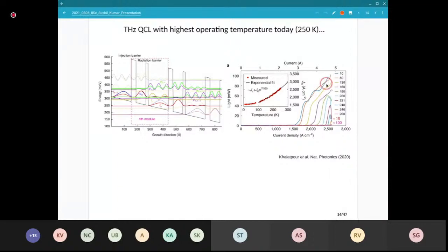But that does not mean that you can just cool them with some cooler and have them working. This kind of figure, I'll show you some more of. This is current and this is light. That's how a laser is typically characterized. These are called LI curves, light versus current. When you keep increasing the current through this device, it starts to lase and emit light. This is laser light, and the power keeps increasing up to the maximum it can reach, and then suddenly drops because something happens and it does not work anymore.